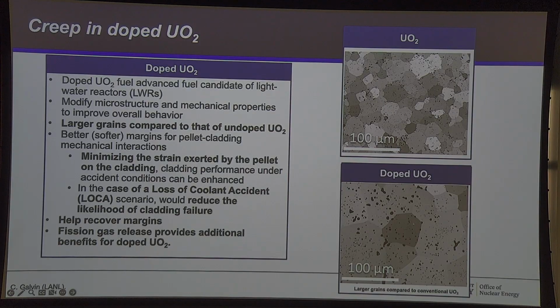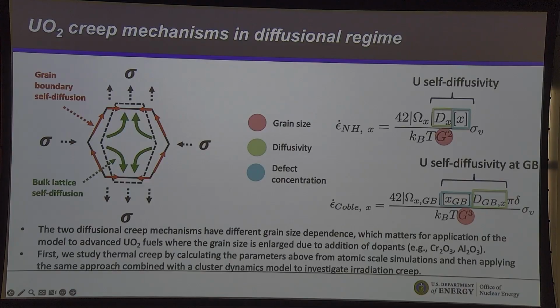That matters if you were to have an accident, and it helps provide more margin for the breach of the cladding. However, in order to take advantage of that, you need a model that can quantify how much it creeps, how much less it pushes. And for diffusional creep, it turns out if you go through the literature, there's still a debate whether this is Nabarro-Herring creep or Coble creep. That essentially means Nabarro-Herring is diffusion goes through, if this is a grain, diffusion goes through the middle of your grain, through the bulk, or it goes through the grain boundaries.